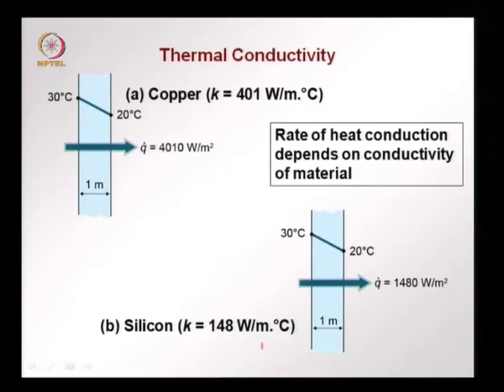Thermal conductivity varies significantly between materials. Say in the case of copper with a conductivity of 401 watt per meter degree Celsius, we can have a case that we have, say, a panel. On one side the temperature is 30 degrees, the other side the temperature is 20 degrees and the thickness is about 1 meter. This would be the rate of thermal conductivity or heat transfer. In the case of silicon, a similar element, silicon has a much lower thermal conductivity, we see that the heat passes less.